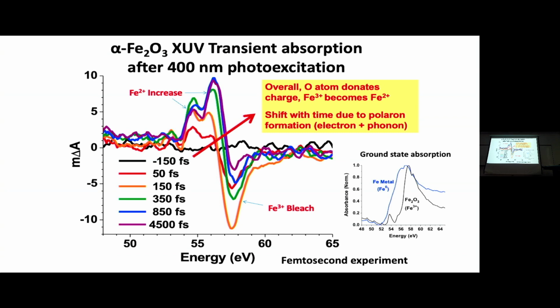So if I perform this experiment and I look at one of these peaks decreases and one of these peaks increases here, we see the iron 3 plus is disappearing and the iron 2 plus is increasing. So we already have a new piece of information that when we excite this material, it's a charge transfer from the ligand to the metal.